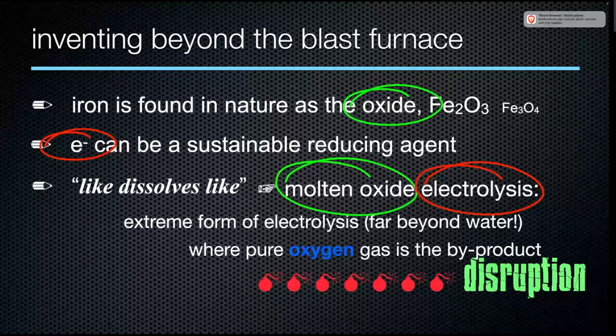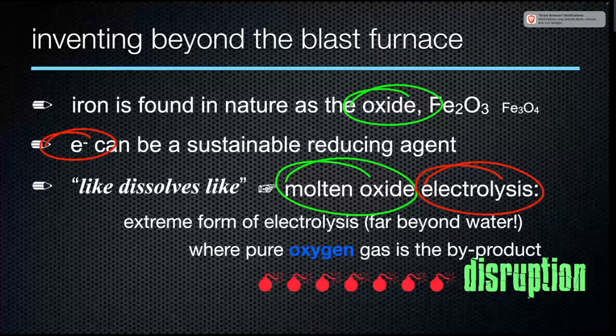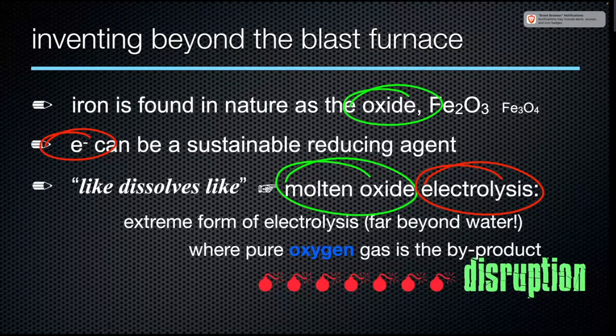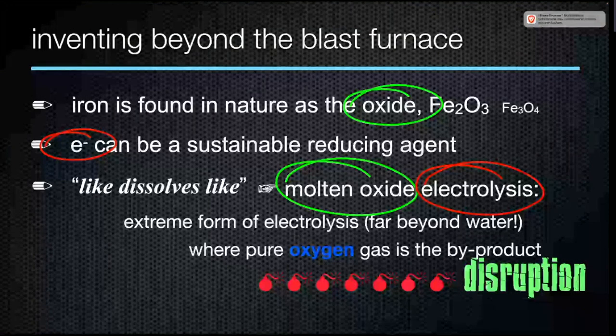It looks like other electrolysis, but far beyond water. Maybe the closest relation is aluminium, where we use aluminium oxide, again, an oxide feed, but we don't use an oxide solvent. We use a fluoride solvent. But here, we will make pure oxygen gas as the byproduct. And if we do that, that's going to be a big disruption because we're going to displace the CO2 emissions with oxygen. So you have two products.